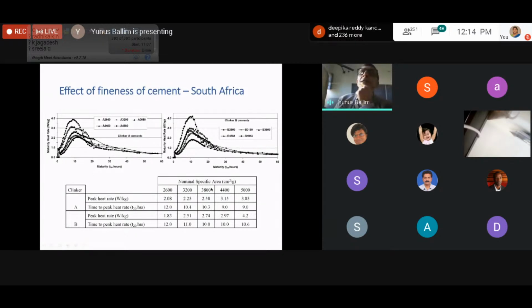And here you can see this is the nominal specific surface area. That would be typical for South African cements. If you bought a pocket of cement in South Africa, it would probably be ground to about 3,200 square centimeters per gram. That is a very, very finely ground cement. You can see the effects of the peak heat rate. So if you want to control peak heat rates and temperatures in your concretes, be careful with grinding.